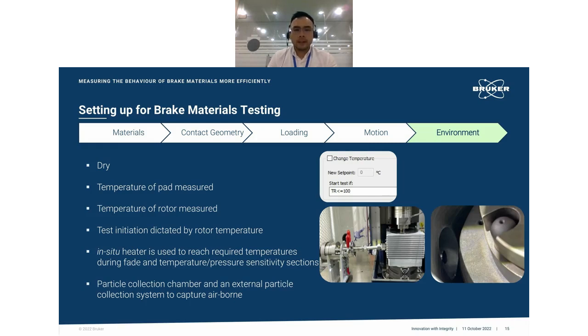So for our case, we use an in-situ heater to reach certain elevated temperatures, especially during the fade and temperature pressure sensitivity sections, where we have direct heating on the rotor disc, and we minimize the heating on the brake pad so that the material integrity of the brake pad is not affected by thermal degradation or change of behavior.